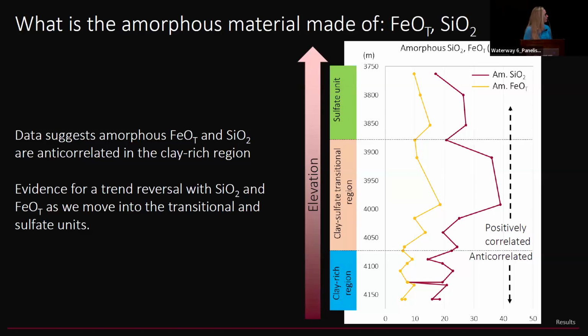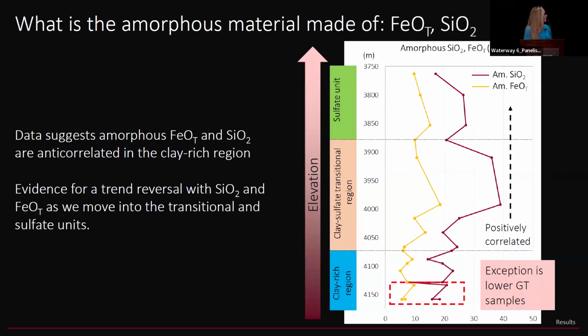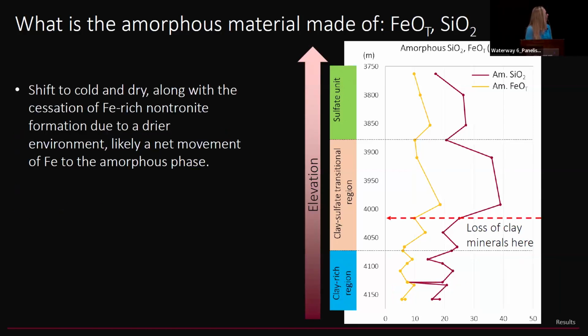The first thing I want to point out is the relationship between silica and iron. In the Glen Torridon region, they appear to be anti-correlated. And then where we lose these clays around here, this relationship changes and they appear to be positively correlated and the patterns sort of follow each other. I think this trend reversal, with the exception of the lower Glen Torridon samples, which is something I need to look at as well, happens around when we lose the clay minerals. And I think, again, this is a shift to a cold and dry environment.